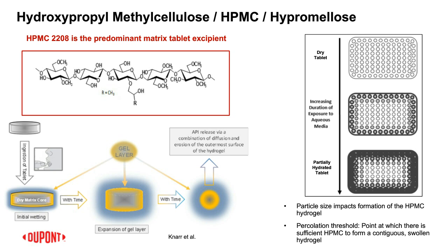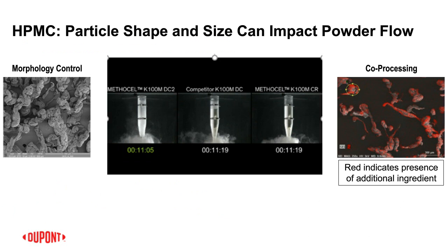As I go to the next slide here, well, particle size is not only important to robust modified release performance. As Yeli mentioned, particle size, regardless of whether we're talking about microcrystalline cellulose or in this instance hydroxypropyl methylcellulose, particle size can impact processability as well. And there are a number of ways to modulate processability of your hydroxypropyl methylcellulose, which can translate to modulating the processability of your overall formulation. You can manipulate the morphology of the HPMC particles, so you can make them more granular, more spheroidal. You can increase their particle size a little bit.